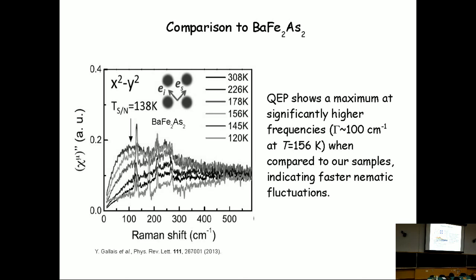Yeah, what I try to point out is that most groups understand that the nematic phase transition temperature is defined as the orthorhombic phase transition. So the nematic fluctuation should have a peak at the nematic phase transition. No, hold on. That's the phase changing temperature. So that's the temperature when the symmetry is broken. So right above it, of course, you expect critical behavior, right? You expect some kind of onset. Nobody says that below which you cannot have another onset.